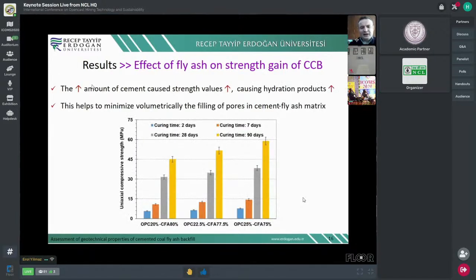And here another result, the effect of fly ash on strength gain of backfill. So when we increase the cement, automatically you will see the high strength value. It's because of hydration products. Particles in the backfill will connect each other and will close some gaps, which will reduce the pores. Later on, you will create a high density material, which will give you the high UCS value.